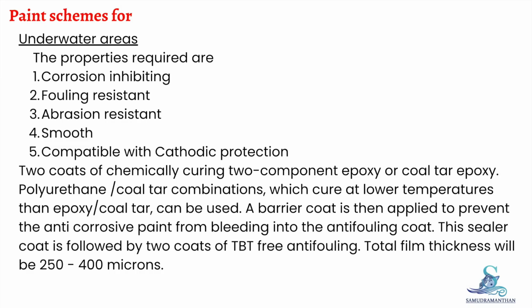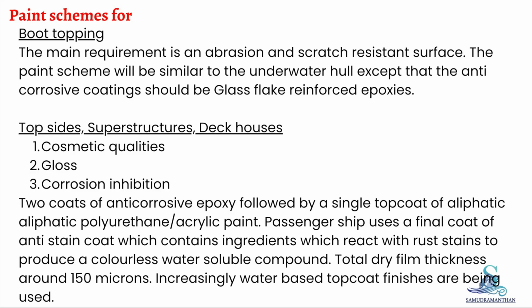Paint schemes for different areas of the ship. Underwater areas. These require corrosion inhibition, fouling resistance, abrasion resistance, smoothness, and compatibility with cathodic protection. Typically, 2 coats of epoxy or coal tar epoxy are applied, followed by a barrier coat and 2 coats of TBT-free anti-fouling, with a total film thickness of 250 to 400 microns. Boot topping. The main requirement is abrasion and scratch resistance using glass flake reinforced epoxies.